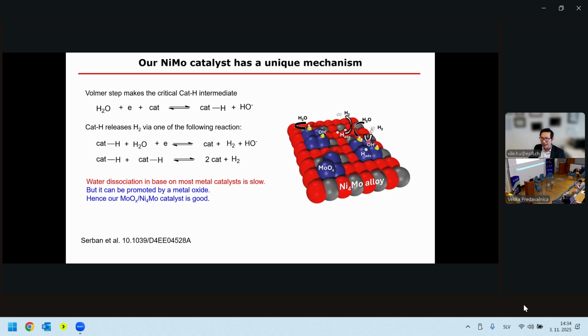So then we basically have protons, okay? Then the proton will be taken by the metallic species to make adsorbed hydrogen species. And so from there, we make hydrogen. And so our structure is important for the observed activity in the sense that we do have, again, cooperative catalysis from metal oxides over a metal catalyst.